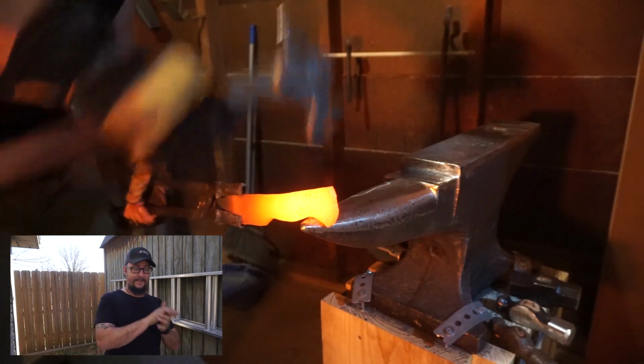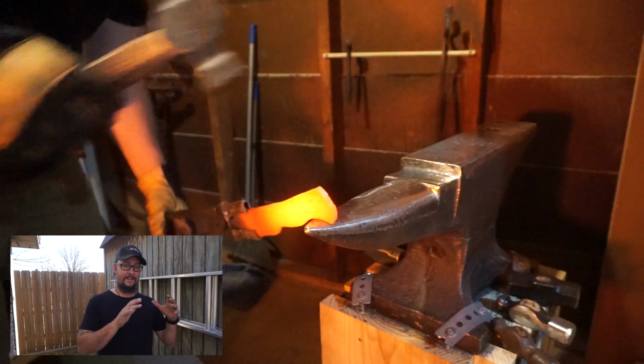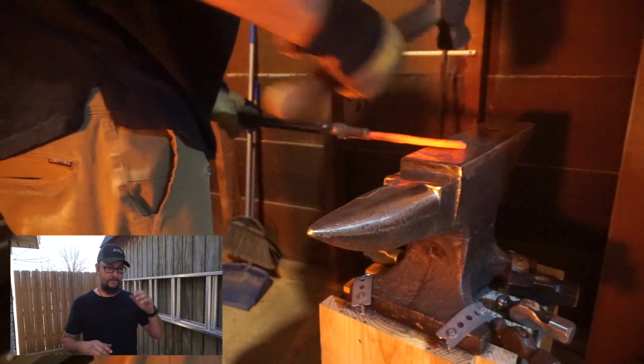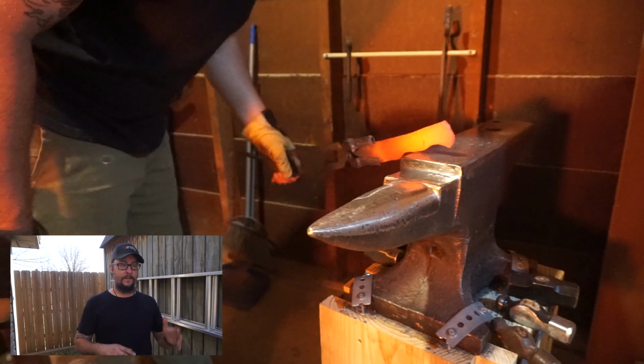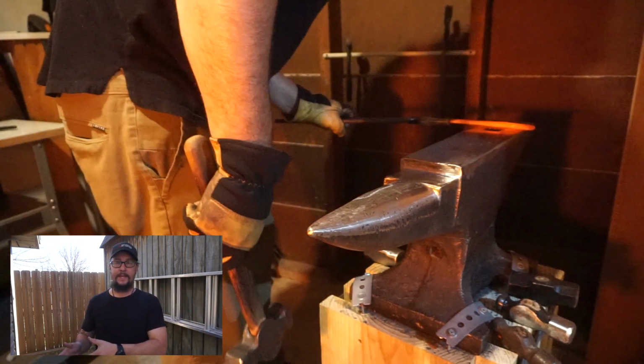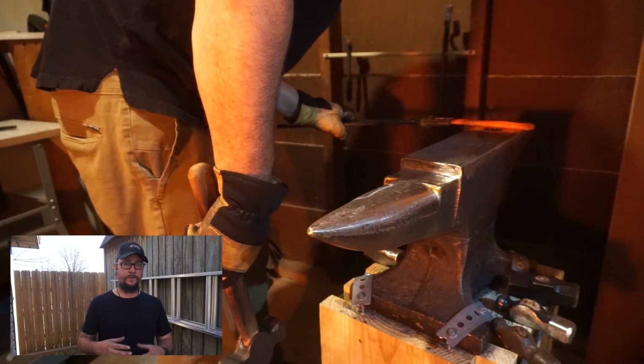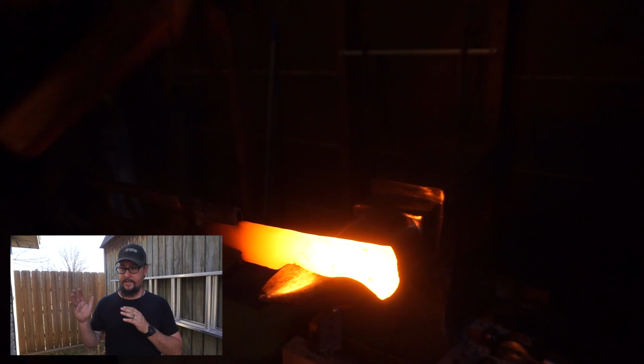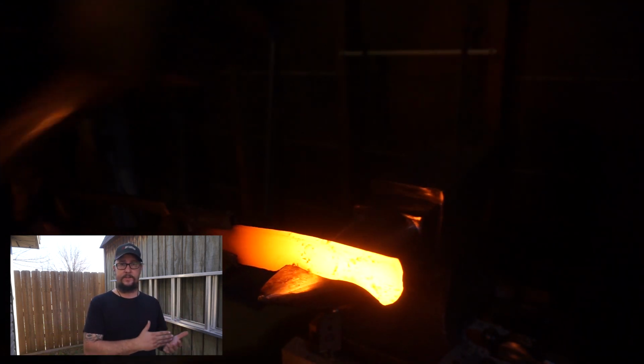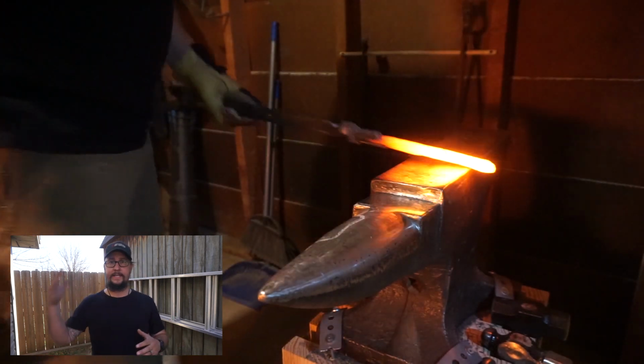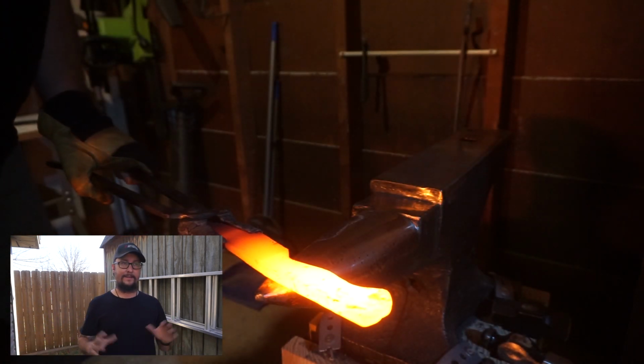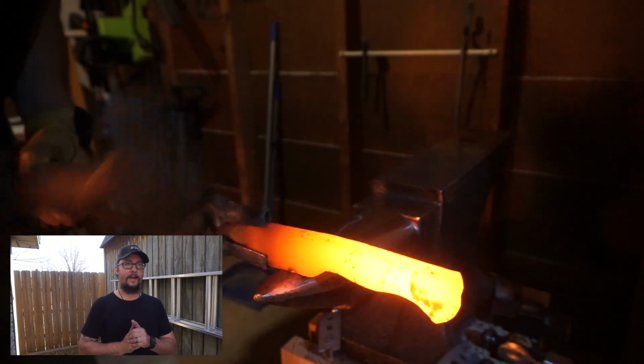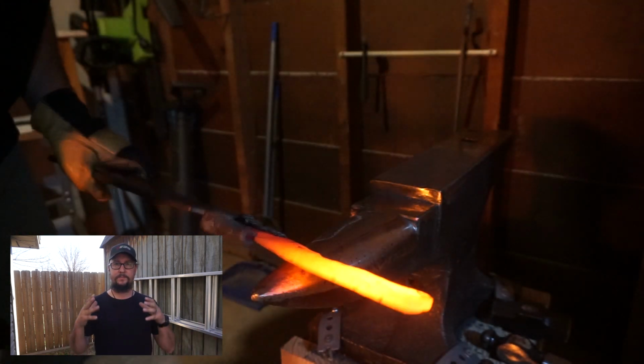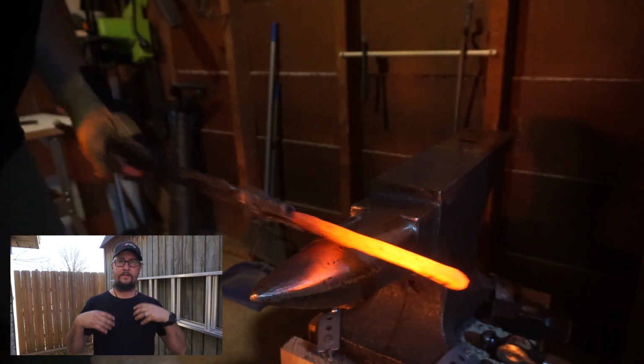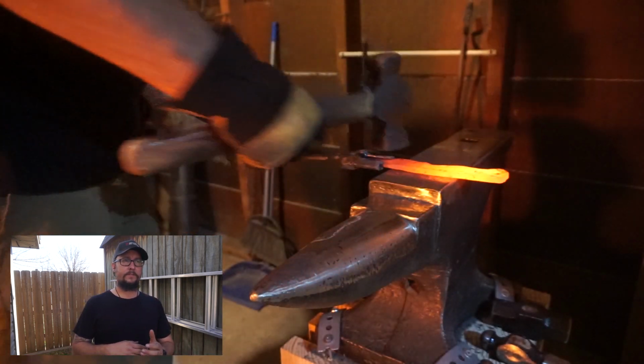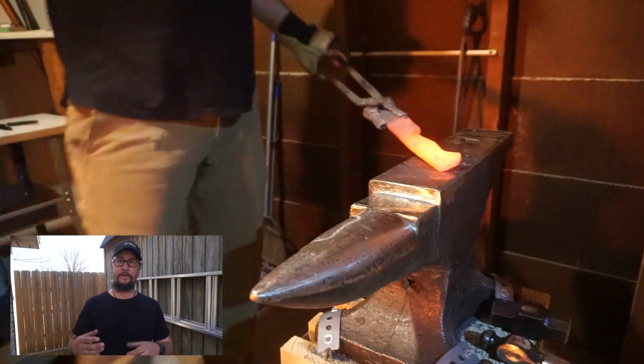But when it comes to tempering, the process that you want to do is your heat treat. So you want to heat it up, get it in the quench, and then within an hour, very soon after your heat treat, you want to get it into the oven and start tempering it. You do not want to wait until the next day and temper it then. It kind of just is useless at that point. Will it help a little bit? Maybe, but it's not doing the process that is actually going to benefit the knife the way that it needs to. So a lot of people temper different ways.